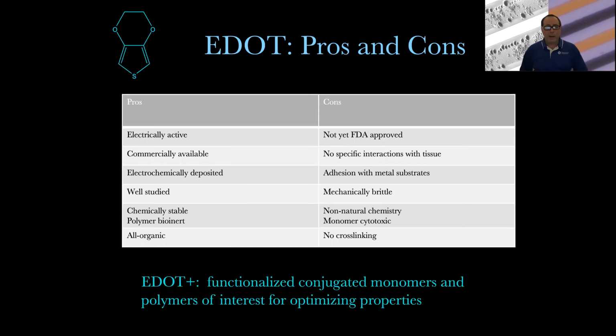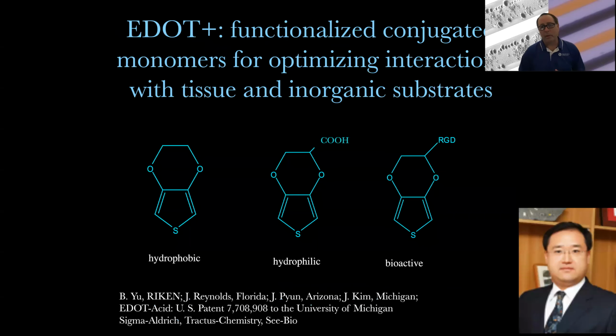The normal EDOT monomer is relatively cytotoxic, and there's no way of changing the mechanical properties all that much. The only reaction that occurs is the polymerization or reaction across the thiophene. And so our new monomers have addressed all of these different issues. One of the first new monomers that we developed, back still at Michigan, was the carboxylic acid functionality. My colleague Jinseng Kim helped to create this EDOT acid monomer that we have been examining in some detail